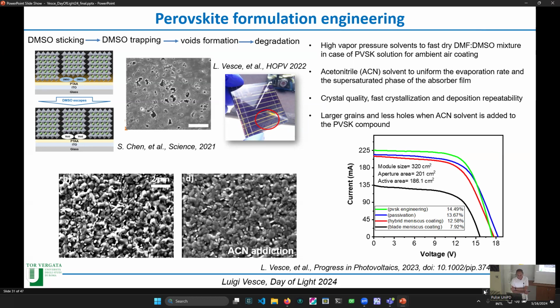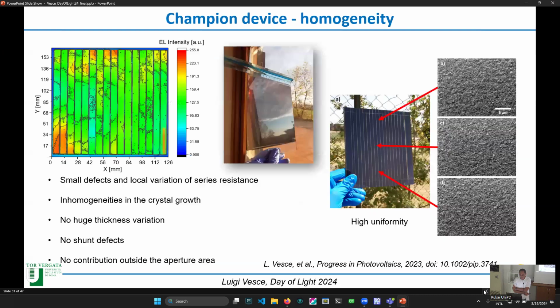Also, you can see from the SEM that you have a larger grain if you add this acetonitrile, that justifies the good formation and growth of the perovskite. In this case, we got 14.49% efficiency, so further improving the results.